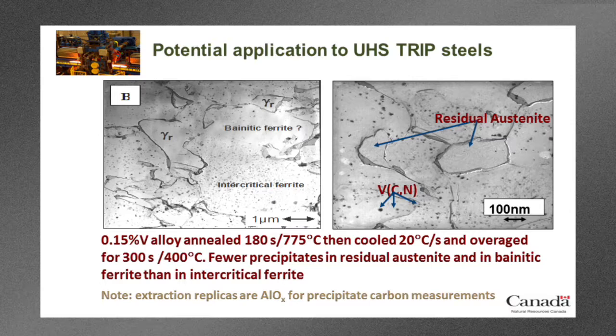If you look at this microstructure here on the left-hand side, it's very interesting. You can see it's an extraction replica. Obviously, I should have said that. You can see residual austenite islands. You can see areas which we think are intercritical ferrite, and you can see other areas that we would assign to bainitic ferrite. The distribution of precipitates is very heterogeneous.